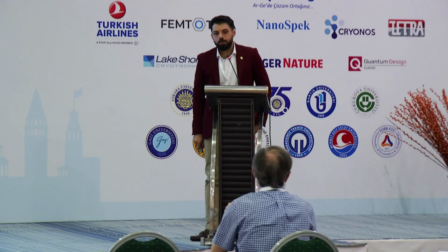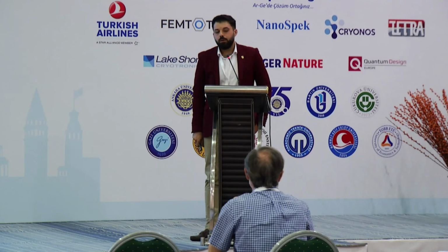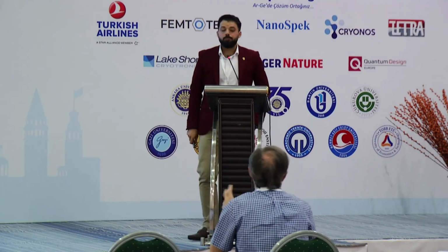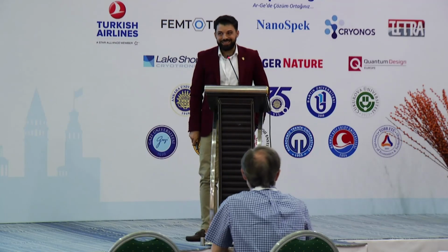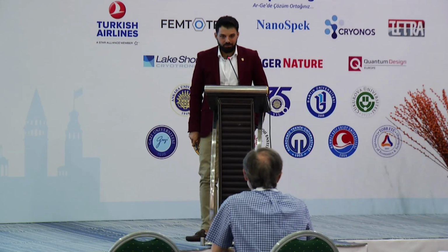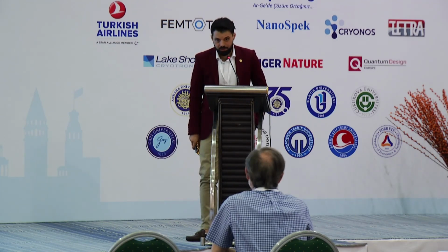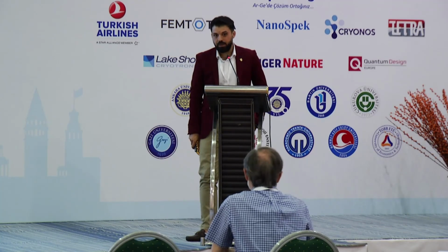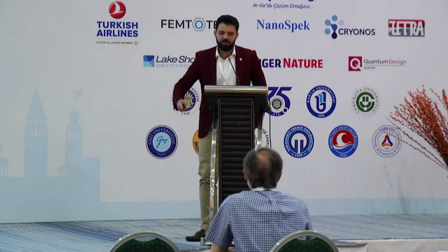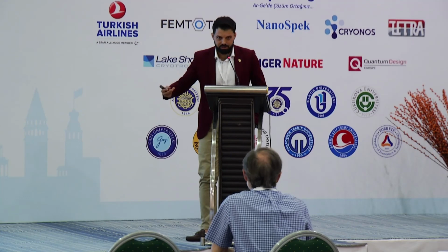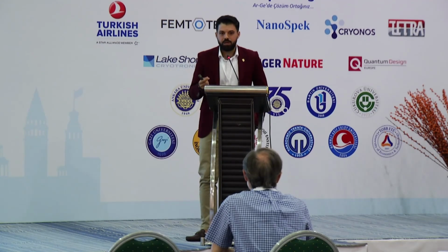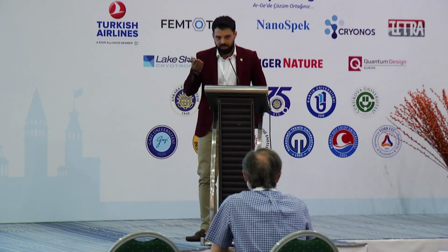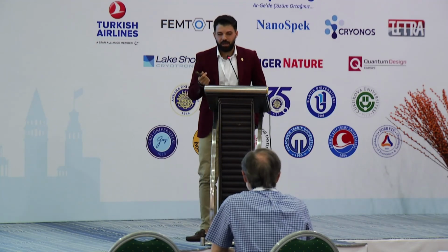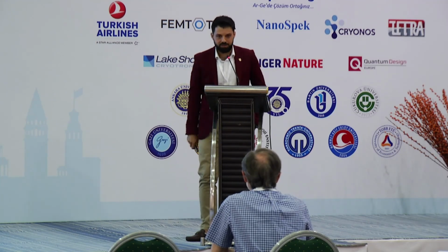Do you suspect that you could have cobalt ferrite synthesis in the grain joints, where you observe necking or any of these phenomena? Yes, actually, we tried to look for impurities using XRD, but we didn't detect any. This is why we're now trying to do Raman spectroscopy, because it's more sensitive. And the anisotropy parameters are very sensitive to impurities, so we left the discussion of these parameters for further investigation after studying the cationic distribution and from the Raman spectroscopy.